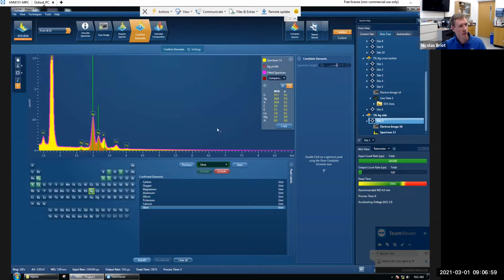Okay. So what that indicates to me is that, yes, there is silver at the surface of the sample. I'm not exactly sure how deep it goes. I know that when I do EDS on a material, depending on the accelerating voltage, the electron energy we use to create the signal, we're thinking about maybe the first micron being probed. So if we see silver, that means there's silver in the first micron. It could be the first 20 microns. It could be the first micron.